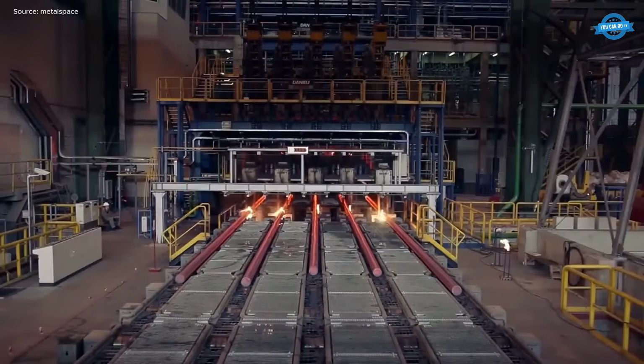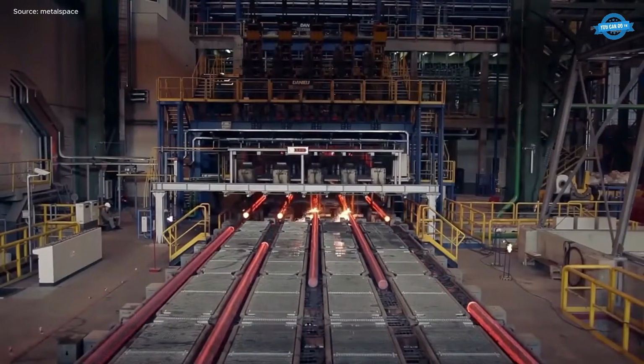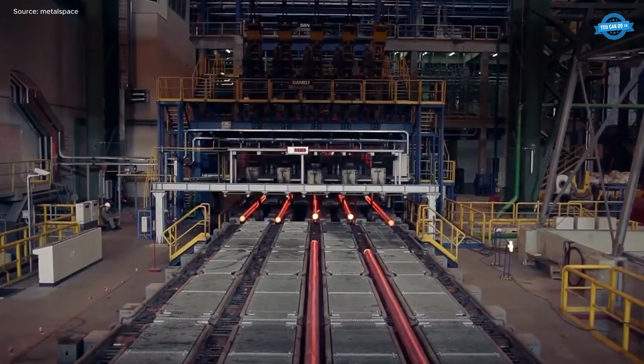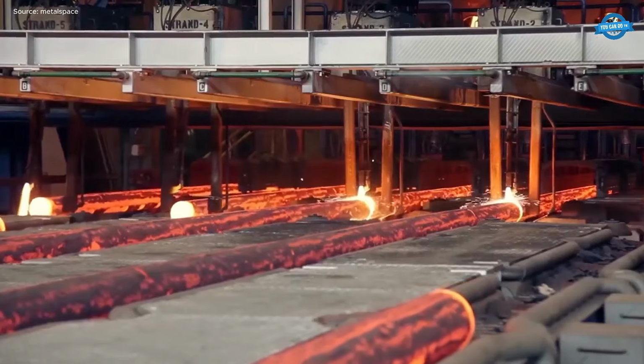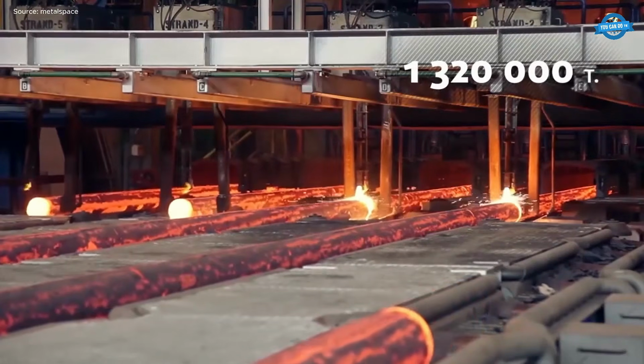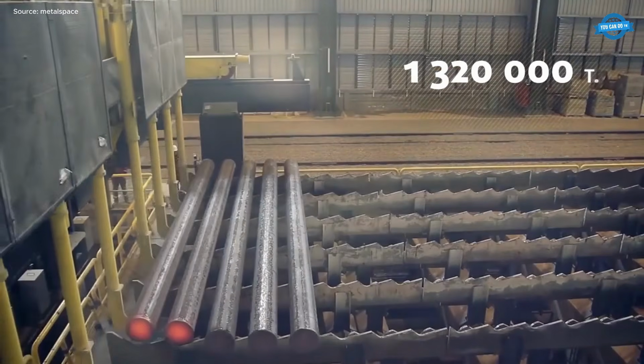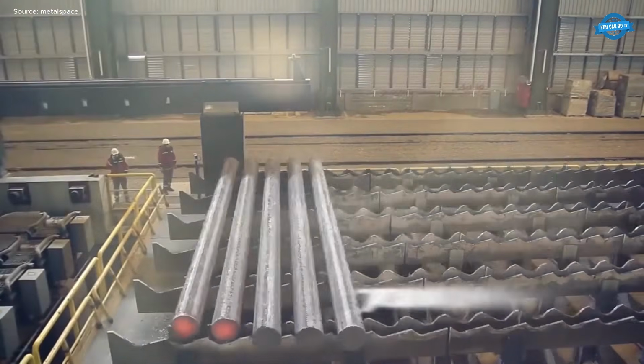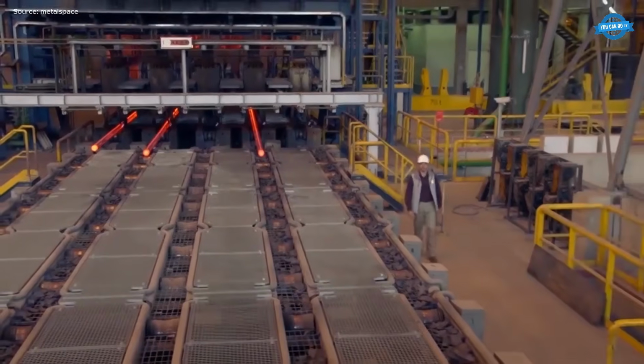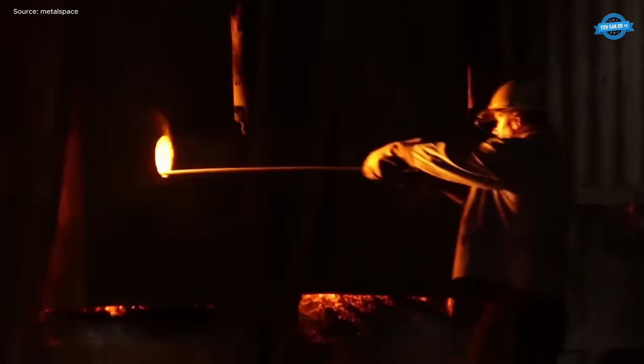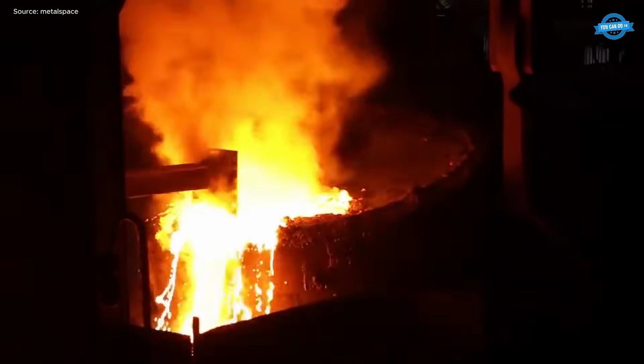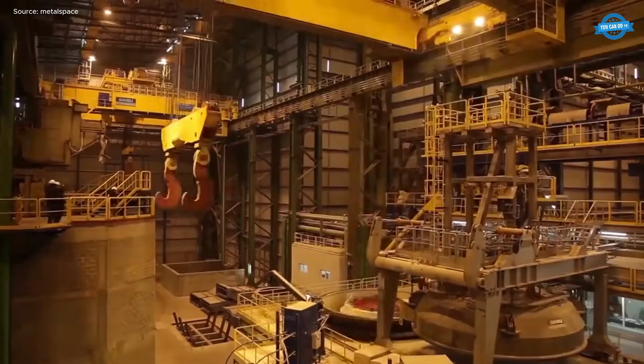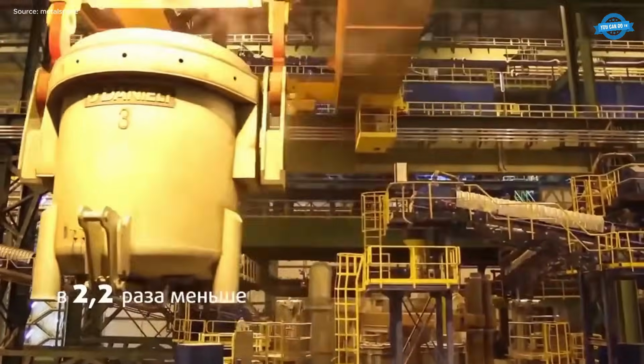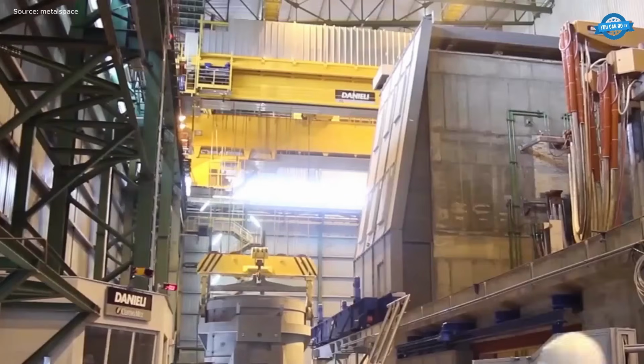Interpipe Steel is a state-of-the-art electric arc furnace, EAF steel plant designed for high-efficiency billet production. With a melt shop capacity of 1.32 million tons per year, the facility operates using scrap metal as the primary raw material. The process begins with precise scrap charging into a 120-ton EAF, followed by refining in a ladle furnace, LF, to adjust chemical composition.